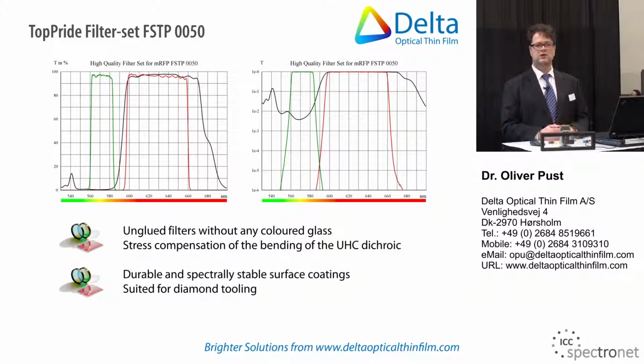All our modern constructions are unglued filters without any color glass. For our dichroics we can apply a stress-compensating coating on the backside to keep the thin dichroics flat for good imaging quality. The coating is durable and stable, so it can be tooled after coating to whatever size is required.